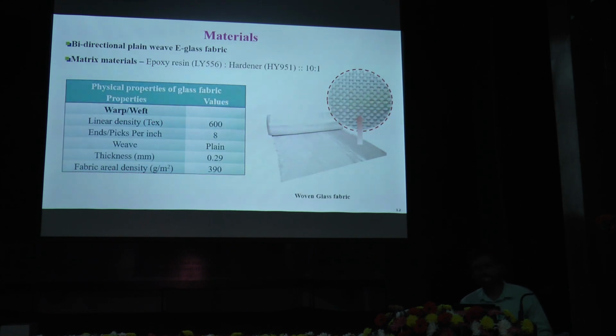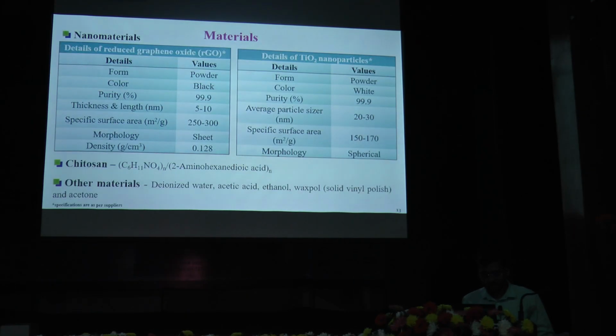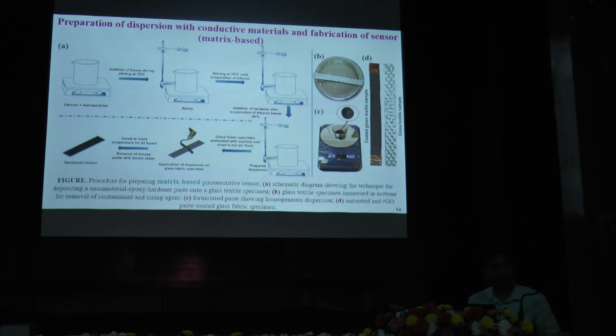At NIT Jalandhar, we are using glass textile as a substrate and epoxy resin as a matrix material to develop these strain monitoring sensors. The nanomaterials we use for creating the conductive pathway include reduced graphene oxide, titanium dioxide as a semiconducting material, and chitosan. We have developed two methods: a matrix-based method and a coating-based method.